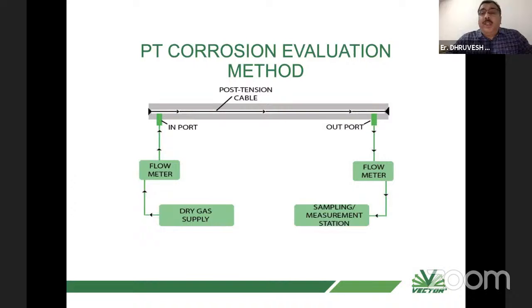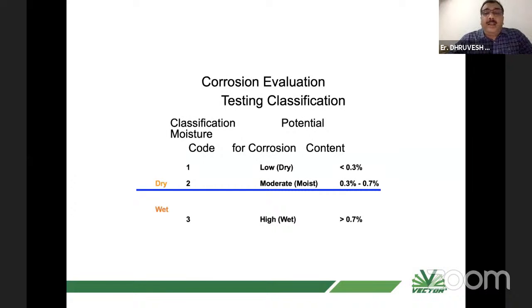One evaluation method is how we know whether moisture is there or not. We call it the PT corrosion evaluation method. We select a tendon, simply puncture it at one place, and insert a port, and there is a flow meter and a dry gas supply. We supply the dry gas, we measure the gas going inside, and at the other end the gas comes out, and then we measure the moisture content of that gas, and it will show us the moisture level inside the PT tendons. As I said earlier, if the moisture is more than 0.7%, it is wet, and it is considered a highly corrosive condition.